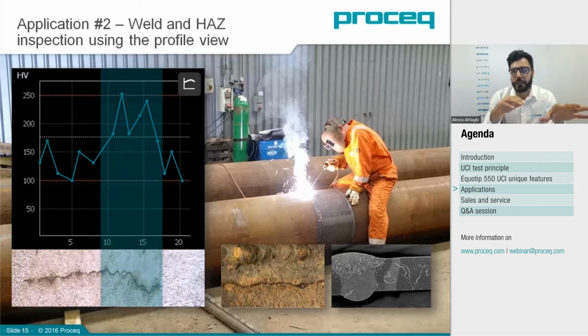What we have done with the UCI, we started with the base material from the right, as you saw in the animation, and started doing testing, reaching the heat affected zone and going on top of the weld. In the area that I've highlighted, you can clearly see the crack. And on the right hand side of the highlighted area, you can see the weld, which is in almost perfect condition. But the crack has started from the heat affected zone. If you look at the hardness trend that is indicated for the heat affected zone, you can see that it's significantly harder than the weld and the base material.